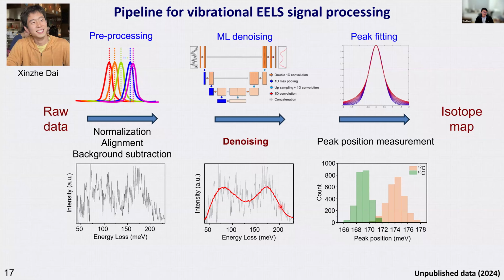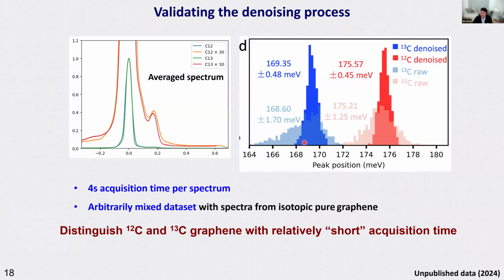Yes, I think that's the core of this work: my student developed this neural network to denoise. And we spent a lot of time testing how reliable it is. Here I only show you one case. We mixed the data from carbon 12 and carbon 13 together and see if after denoising we can still accurately assign, because we know the ground truth of the data. With denoising, in this particular testing, we can assign carbon-12 and carbon-13 100%. And in some other more challenging tests, the accuracy is consistently above 90%.